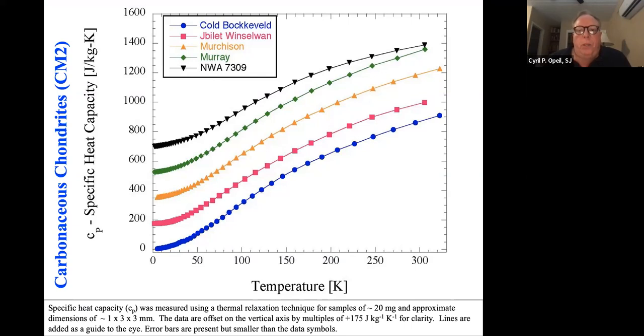Now, this is a well-behaved material. This is specific heat capacity versus temperature. The data is offset. If I didn't offset the data, they'd all be collapsed into kind of a single curve. But what's important here is that there are no major transitions that we can see at this level. There are also no deviations in the heat capacity. If there were a crystal transformation or something really odd going on, magnetic or crystallographic transitions, we would see it represented in these curves. And so it's very well behaved.